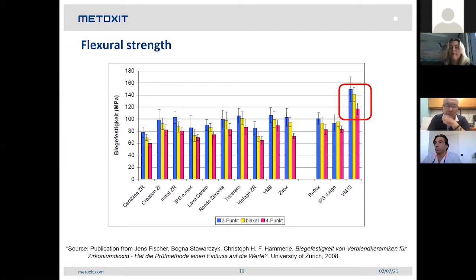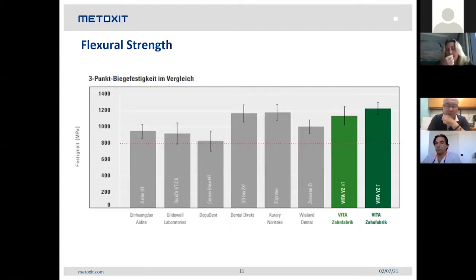But what a lot of companies do is this: they give you tables like this from the 3-point bending test. And now you normally have to correct it, so put all the values 20 to 30% lower, and then you get the right flexural strength. And you see, this 800 megapascal is what you need for stability. And if you decrease these values by 20 or 30%, then you see what you get.